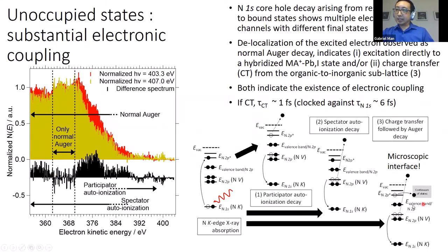What that's telling us is that a lot of these core excited electrons have actually gone somewhere. And we think it's gone into the lead halide sublattice, because our DOS calculations show that the molecular orbitals for methylammonium are pretty delocalized, meaning that the carbon states and the nitrogen states pretty much overlap on top of each other. Either way, the normal Auger decay shows that either we're exciting a hybridized MA lead iodide state, or there's actually charge transfer, where the core excited electron is initially bound to the nitrogen but then goes away within the lifetime of the nitrogen 1s core hole, which is roughly on the order of femtoseconds.